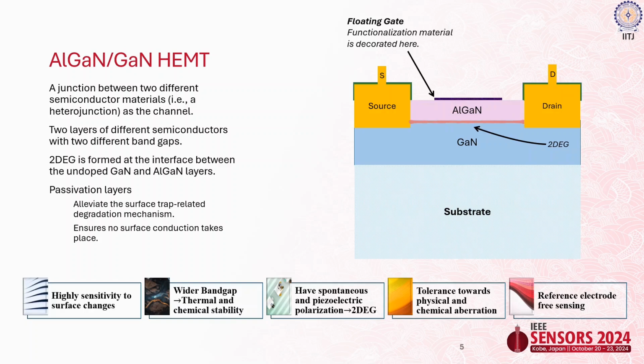So the advantage with this, specifically the III-nitride materials like the AlGaN, GaN, and this family, it has wider band gap, so it has better thermal and chemical stability. So we can use it for a wide variety of uses, in all kinds of environment, even if it is corrosive. Plus, they have the spontaneous and piezoelectric polarization that leads to the formation of the 2D electron gas that acts as the channel.